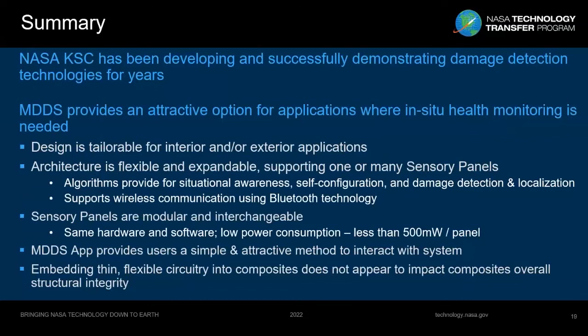It supports wireless communication using Bluetooth technology. The sensory panels themselves are modular and interchangeable. We use the same hardware and software, and they are low power consumption, less than 500 milliwatts per panel. The MDDS app that was developed provides a simple user interface, and it's an attractive method to interact with the system. And the embedded thin flexible circuitry that we used with the composites did not appear to impact the composites' overall structural integrity, based on some imaging and CT scans that we did of the fabricated composite samples. Next slide.